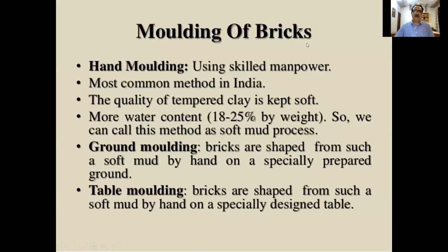The second operation is the molding of bricks. Molding can be hand molding, or ground molding, or table molding of the bricks. Using skilled manpower, hand molding can be done. The most common method in India is hand molding. The quality of tempered clay is kept soft. More water content, 18 to 25% by weight, is added. So we can call this method the soft mud process.